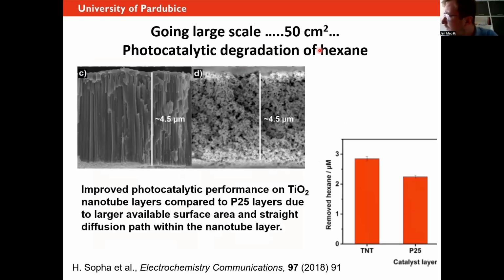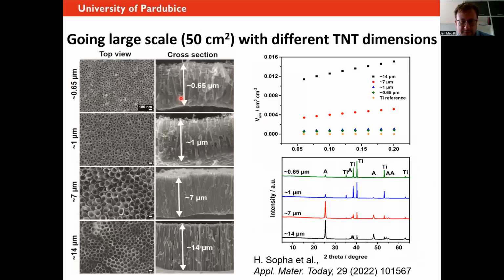Typically, photocatalytic people work with volatile organic compounds like VOCs, because they are dangerous. They are released in households from furniture, from carpets, from many different products. And there are some limits for them, especially for kids, they can be dangerous. So typically you work with hexane, benzene, things like this. And we were again very happy to see that the tubes did the decomposition faster than P25. Once more, we compared here same thicknesses to compare apples and apples.